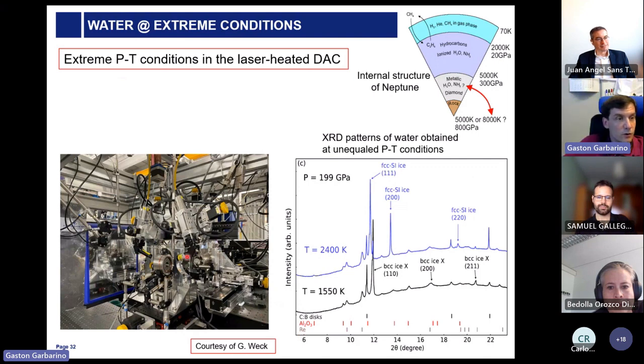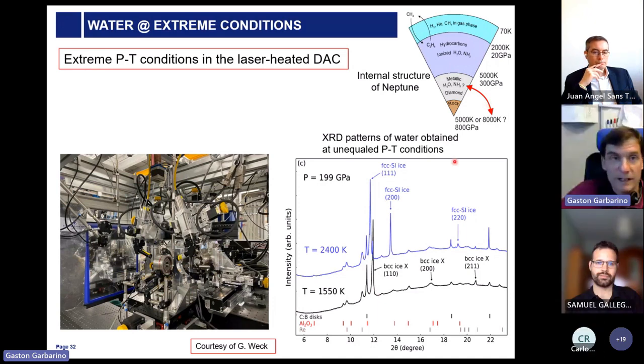So what we can see is that if we compress water and you warm up, you see the appearance of a new phase appearing at very high pressure and high temperature, showing that we have a new cubic phase of ice, of water, that can explain some particular properties that have been predicted in Neptune, for example. So on one side we have the experimental evidence that the new phase of water is existing at this particular high pressure that are very large in terms of pressure and very high in temperature, but also can give some explanation of how these metallic regions in Neptune can be explained with experiments.